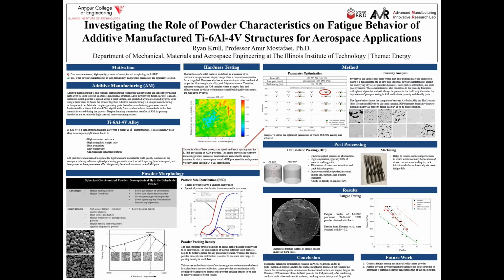These internal defects of a build are known as pores or cavities within the microstructure of the part. These tiny pockets can entrap gases and are where stress concentration is high and results in lower lifespan of a given part. Porosity analysis, as shown here, illustrates the post-process of samples where you can see how significantly reduced and almost 100% elimination of pores within the initial build. Extending further on that is the essence of post-processing, which has contributed largely to the high cost associated with AM. This is why the less post-processing that can be done, the lower the end cost can be. Hot isostatic pressing, also known as HIP, is a post-processing method that basically applies pressure in all directions onto a part at very high temperatures. This helps reduce and nearly eliminate porosity within a part and results in greater than 99% density.